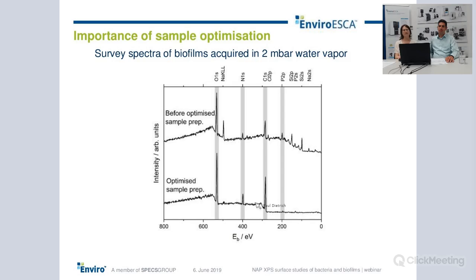To show you again the importance of sample optimization, I here show you 2 survey spectra. One is of a biofilm before optimization, and one is after optimization. They are acquired in 2 millibar water vapor. Before optimization, you first of all have also a signal from the silicon wafer. This is because the bacteria grow inhomogeneously on the substrate, so you also have patches without any biofilm. And then you also have a signal from sodium and chloride, which is from the washing buffer, usually called PBS, and you also have a phosphate signal from the phosphate in the buffer. After sample optimization, you have a strong signal from oxygen, nitrogen, carbon, and phosphorus.